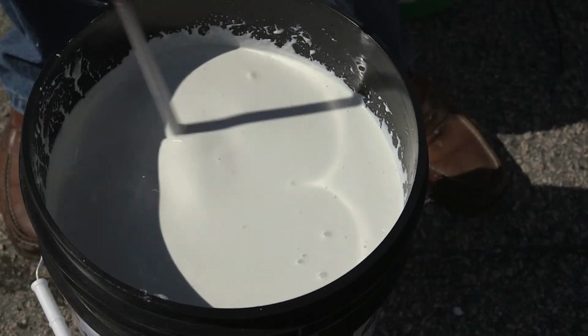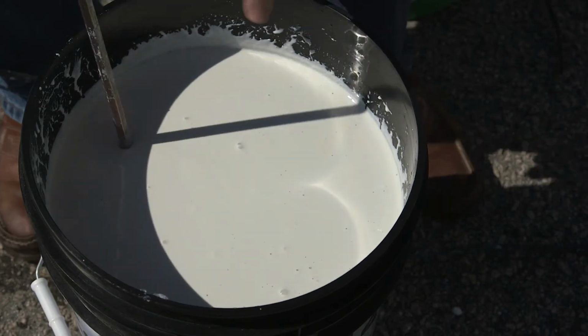You will need to mix the material for about 60 seconds until it is smooth and flows like a liquid. When the material is properly prepared, the viscosity will be about 8,000 centipoise, and Part A will flow like molasses. Look how smooth Part A becomes in about a minute, and it is now ready to use. Keep in mind that if you were to reseal the bucket and leave Part A untouched for about 12 hours, it would return to the gel-like state that you first saw when you opened the bucket.